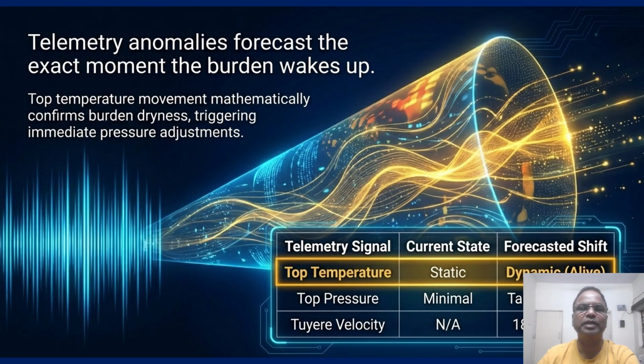It means the burden is drying and moving, and it shows a sort of wavy texture or wavy curves. So at that moment, operators must react quickly to control the pressure and descent, and not try to normalize the furnace as quickly as possible.